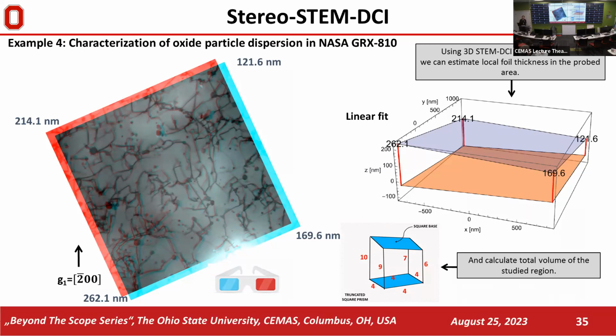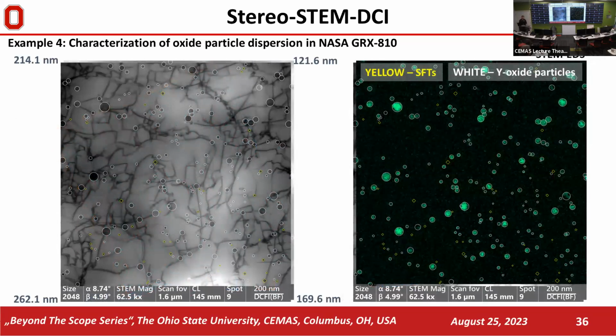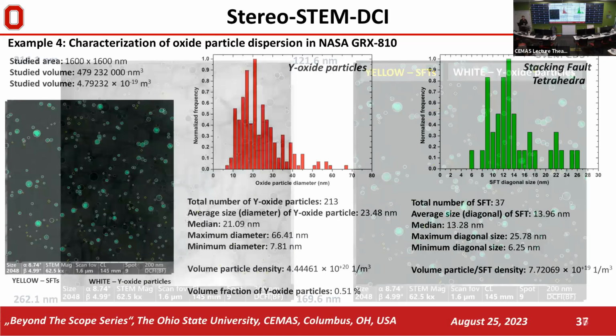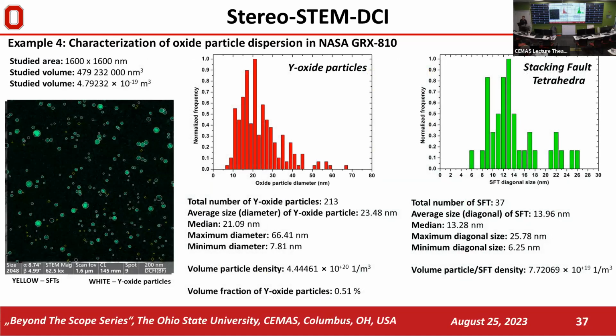So when we know very precisely the thickness of the area we investigated, we can go further and cross-correlate this with STEM EDS, which we collected for the same area, and we can figure out if there is different dispersion of different objects which are important for us. Like in this case of GRX, it's oxide particles and stacking fault tetrahedra. So both are expected to be strengtheners and obstacles for dislocation movement. So we are trying to figure out what's the volume dispersion, what's the average mean distance for these objects. And so we can get the distribution functions out of it. We can get volume, particle density, and fractions of that, which can be used later, especially for alloys which are produced for additive manufacturing.